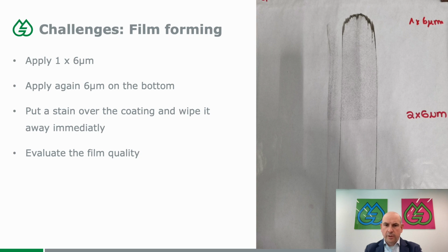And how do we test it? You see here on the right hand side this picture. We apply 6 microns wet, then we apply a second layer, and then we check with a black wiping stain the quality of film formation. In case of the top of the picture, you see the fractures in the film caused by the poor film formation. So the black wiping stain is able to color the paper. And then on the bottom, you see that when you apply the second layer, this disappears.